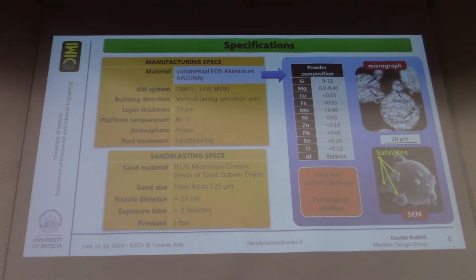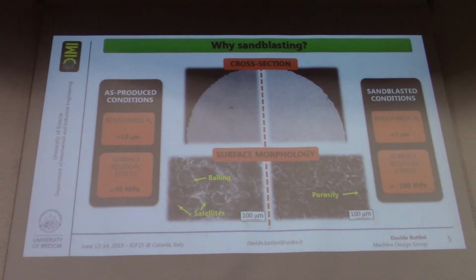We actually carried out some preliminary analysis on the powder, and as we can see, the quality is very good since there is a very low intrinsic porosity with few porosities at a few micrometers level. And as we can see here, sandblasting already looks quite effective since the roughness gets a lot better, as we can see both on the top images and on the bottom images.